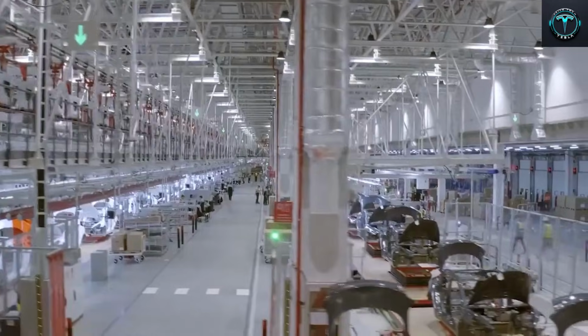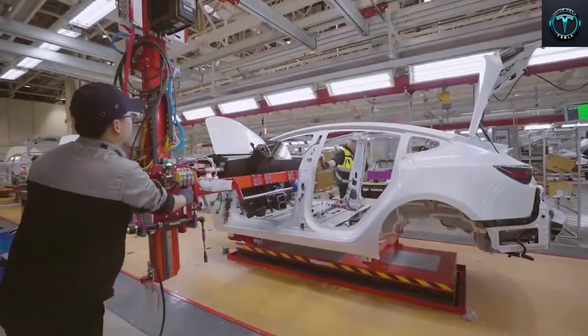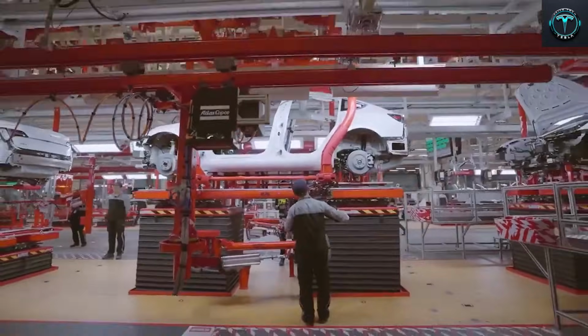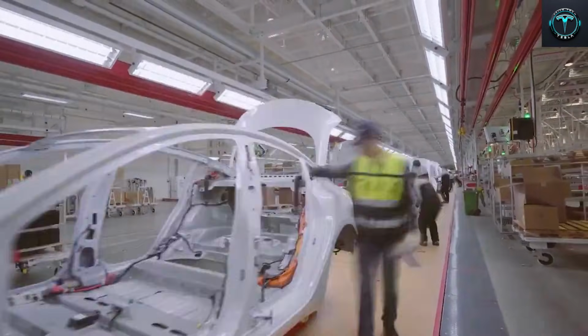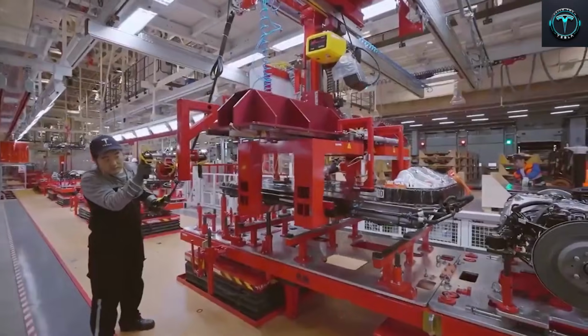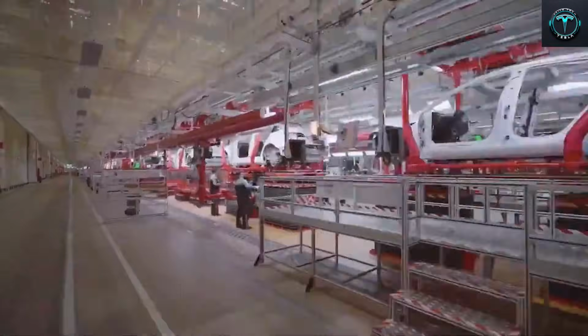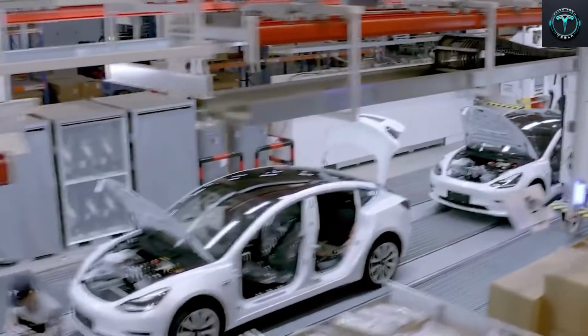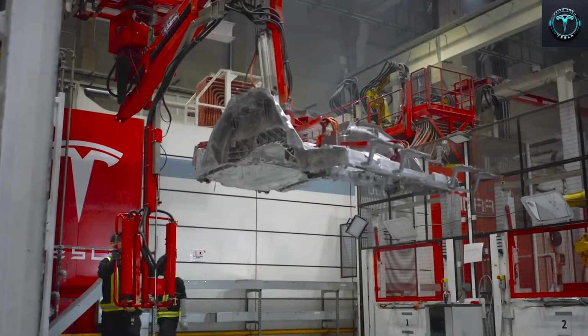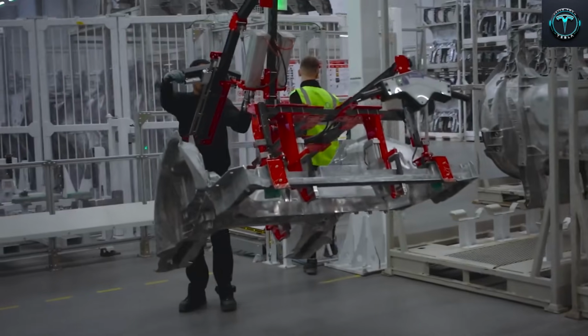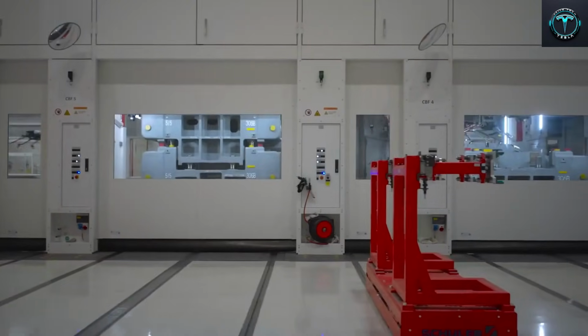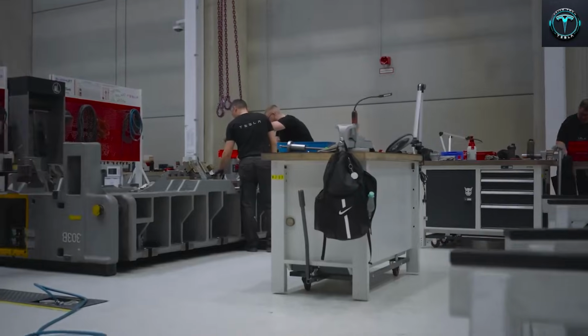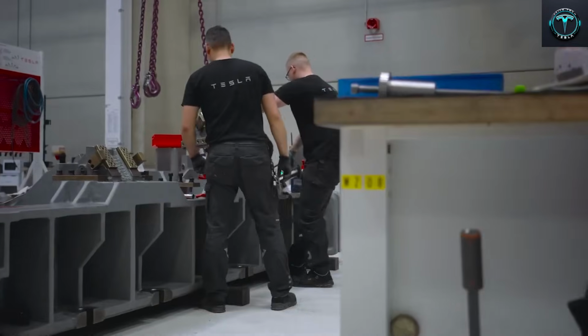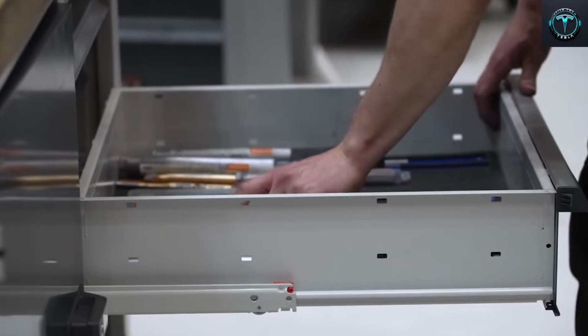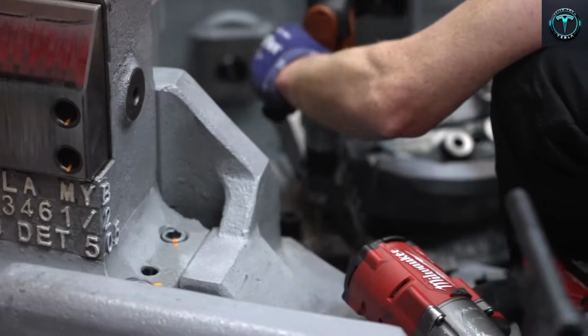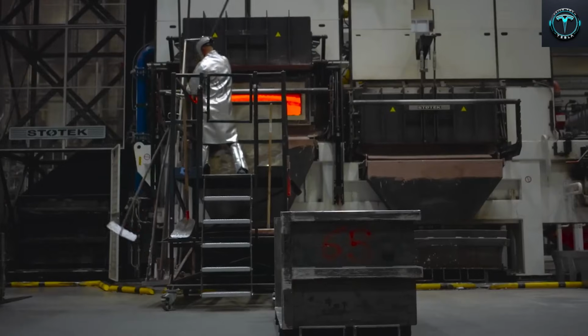The Giga Press solidifies liquid aluminum into a full structural frame in seconds through a highly controlled, rapid process. The cycle begins with perfectly refined aluminum, around 80 kilograms for each mold, stored in the 600-liter holding furnace at ideal temperature and viscosity. Stability is critical. Too hot, and it traps gas; too cool, and it solidifies early. Before injection, the mold surface is coated with a thin release agent for a smooth flow, and a vacuum system pulls out all air pockets. This is especially important for the Model 2's monolithic underbody with its intricate channels.